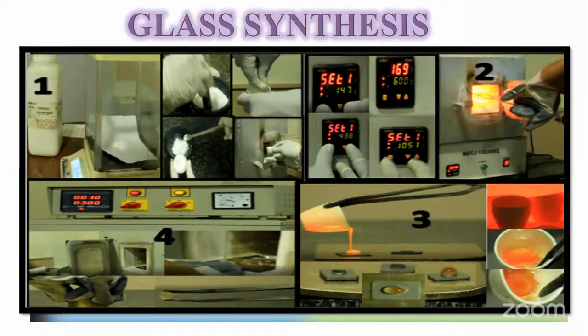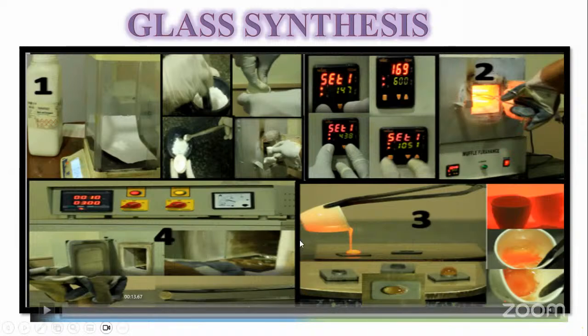And finally, you can quench the sample at 1050, 1100, 1000, or 800 degrees Celsius. Depending on your batch, you can start playing around with the temperature. And once the liquid is formed, you take it out and immediately pour it, and it rapidly solidifies. And once the glass is solidified, again you place it inside the furnace. So that's what you try to do.